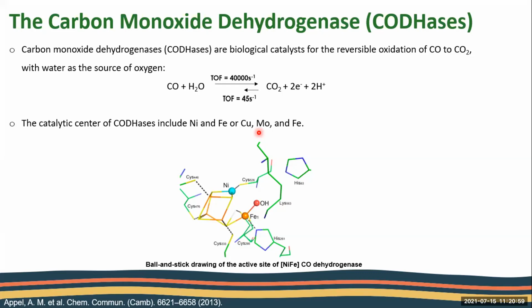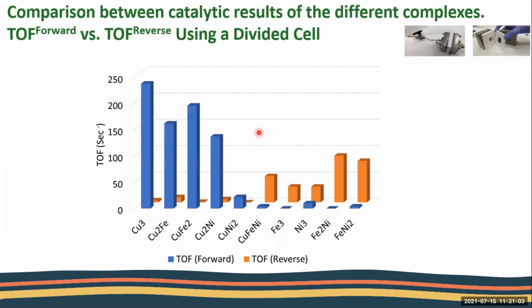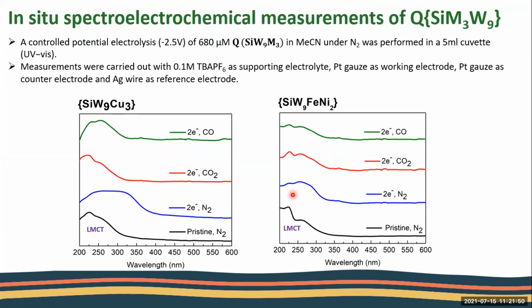In order to check that, we did the reaction in both directions, the forward and the reverse reaction, and compared them across the different combinations. As you can see in this result, the forward reaction rate is highest with copper 3. When we start to add iron and nickel, it reduces the forward reaction. But if you look at the iron nickel family, you have a strong reverse reaction. That means that all the CO that we produce is immediately converted to CO2 as the product. That's very nice because it gives us the idea that we can control the rate of the reaction by changing the metal. And at this point, we go into the mechanism in order to understand how the mechanism of all the complexes works with the reduction of CO2.